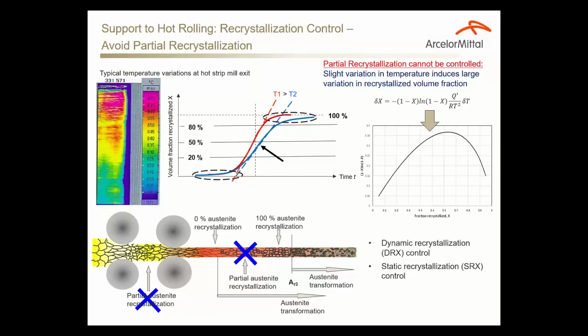Another important application is recrystallization control. When we hot roll the material, the material is recrystallizing because of high temperatures. The goal of any hot rolling is to avoid partial recrystallization in the final product because partial recrystallization cannot be reliably controlled. Very slight variation, say in temperature of the bar, can change the volume fraction recrystallized, so we can obtain very non-uniform microstructure in between the passes, during the rolling pass, after exiting the mill. So the transformation of microstructure will also be affected.